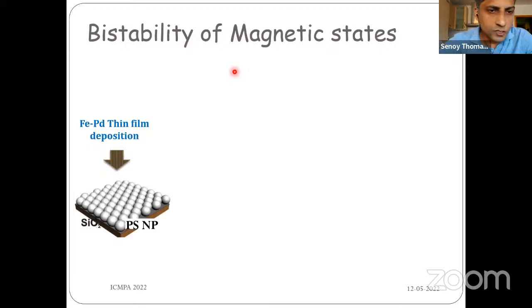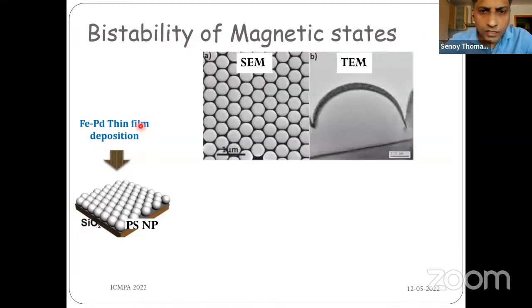And for that, we chose the iron palladium alloy system, and we deposited an array of polystyrene nanoparticles, which have a fixed diameter, with iron palladium thin films having different compositions with a thickness of 20 nanometers. Here is the scanning electron micrograph, which shows the ordering of polystyrene spheres on top of a silica substrate. And on top, we have deposited iron palladium alloys, which is basically forming the so-called magnetic cap structures, which one could see from the cross-sectional transmission electron micrograph image.